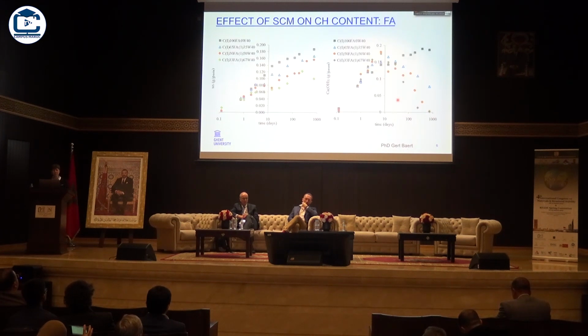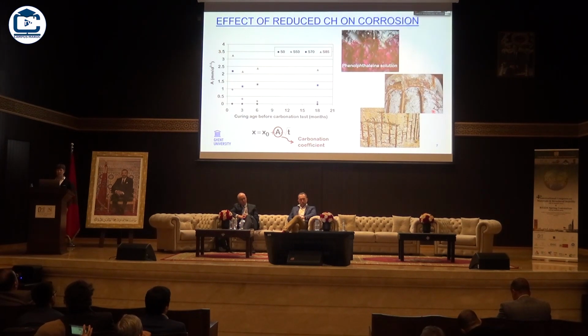But if you move to the use of fly ash, for instance, then you can clearly see, if you would use higher amounts of fly ash, going from 30%, which is more often used, to higher amounts like 50%, 65%, that over time, after a few years, actually the Portlandite content goes down to even 0. And this, of course, has some effects on carbonation resistance because Portlandite is an important buffer towards carbonation. And we can see that for mixes with supplementary cementitious materials, carbonation rates are increased, and this might lead to faster corrosion of reinforcement once the carbonation depth reaches the reinforcement.